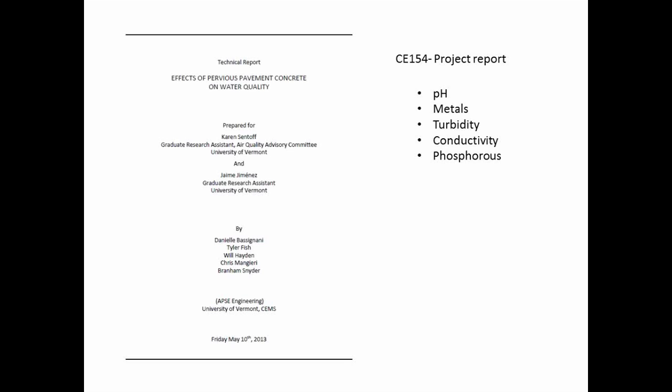From what I've seen on that lot, there was some soil carried in on a lot of car traffic, and that has an active collection system, so the asphalt runs onto the concrete, like in this lot. And I've seen much higher clogging and reduction in infiltration capacity, which would increase the saturation of that top layer, because the soil clogged in there is going to remain saturated through that freezing and thawing. So I like to say that anything that increases the saturation of the pervious concrete will result in damage. So clogging, the presence of salt, if there's not proper drainage below the system, if you didn't include enough storage capacity, some of those things.